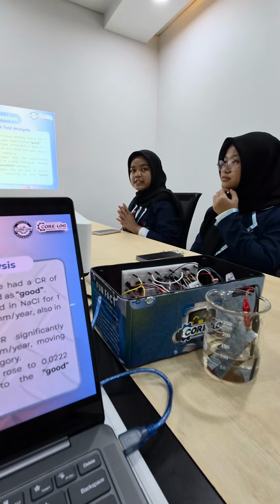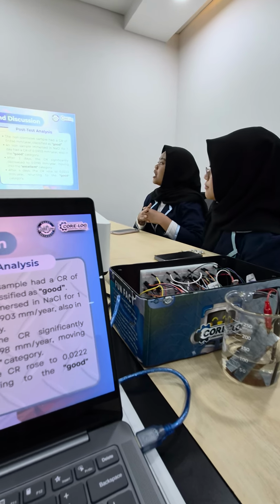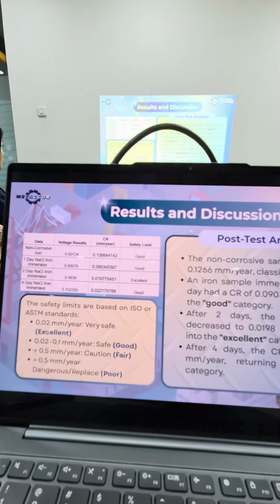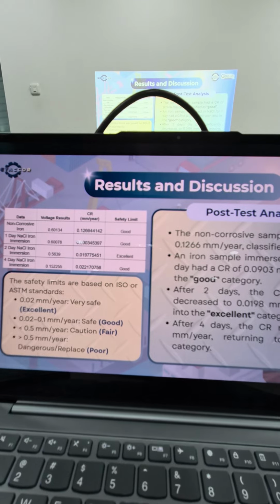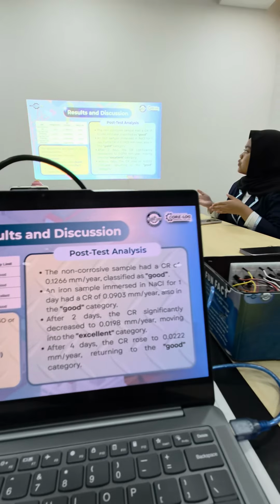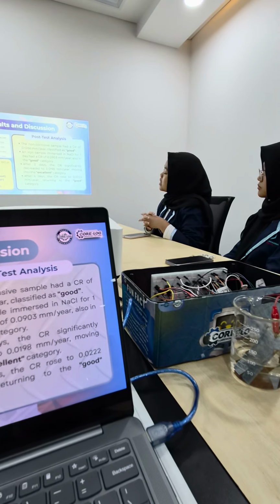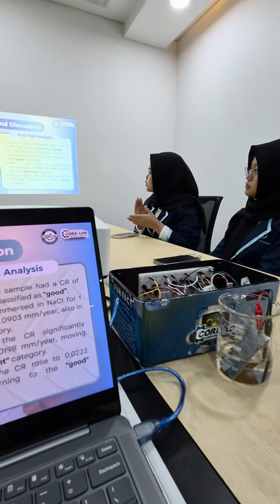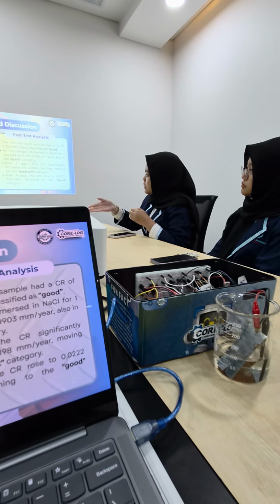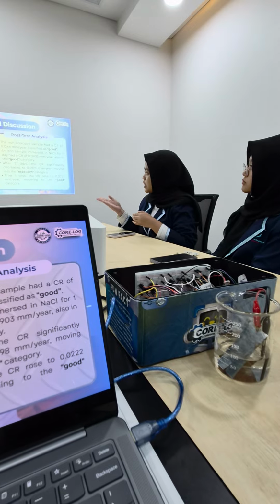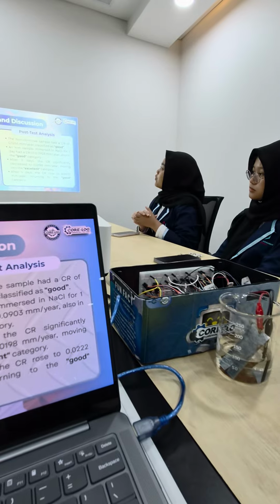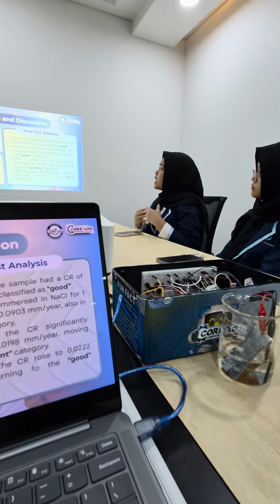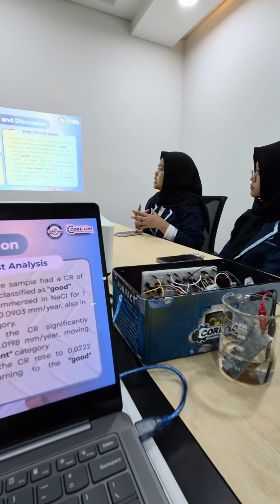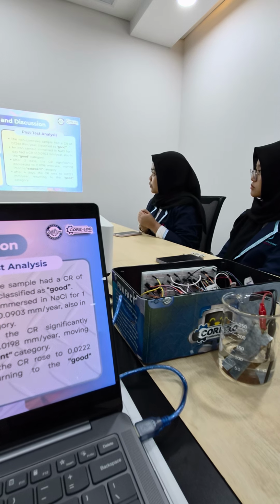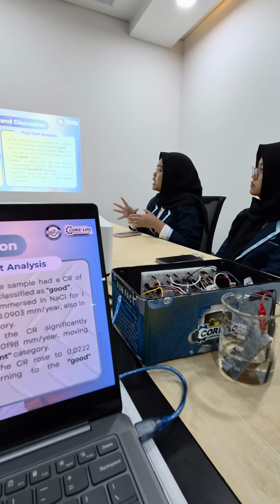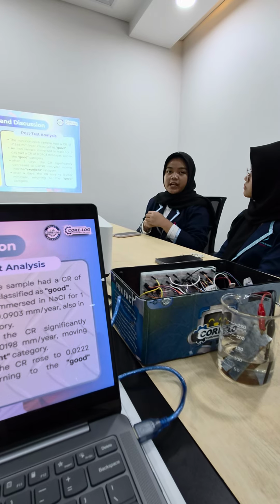And for the last result and discussion, we test post-test analysis from corrosion rate based on safety limits from ISO or ASTM standards. If we see from the first data for non-corrosive iron, the corrosion rate is 0.1266, which, based on the safety limits from ISO or ASTM standards, is classified as good. And for the second data, 1-day sodium chloride iron immersion, the corrosion rate is 0.0903. When we see the safety limits from the ISO standards, it's classified as good.